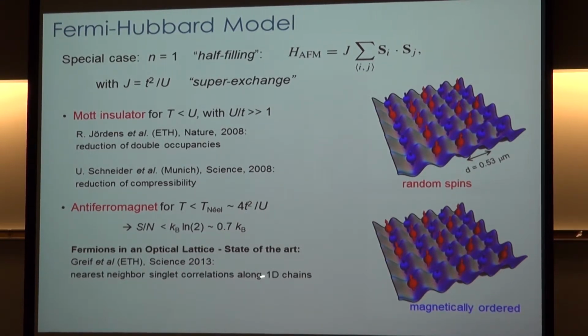So the state of the art in an optical lattice is in Tilman Esslinger's group, where they've seen nearest neighbor singlet correlations along an anisotropic lattice. So they effectively made a series of 1D chains, and they are able to get to temperatures that are about 3 or 4 times this Néel temperature.